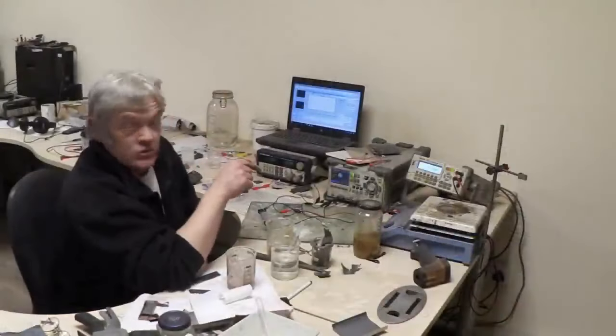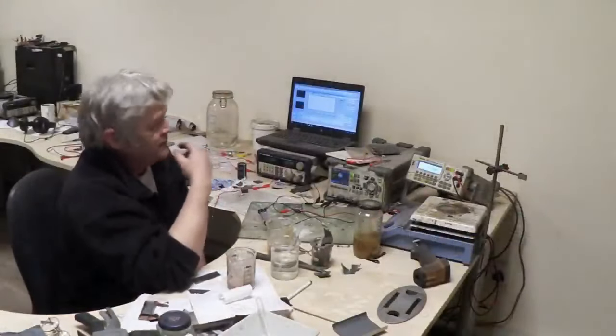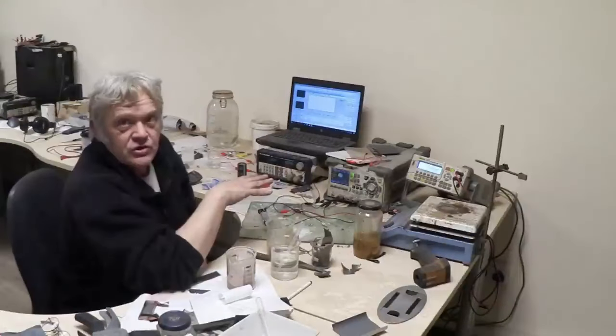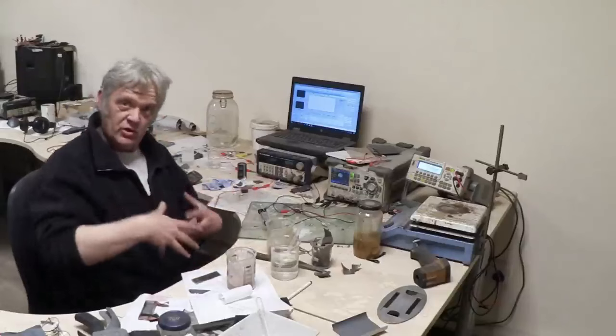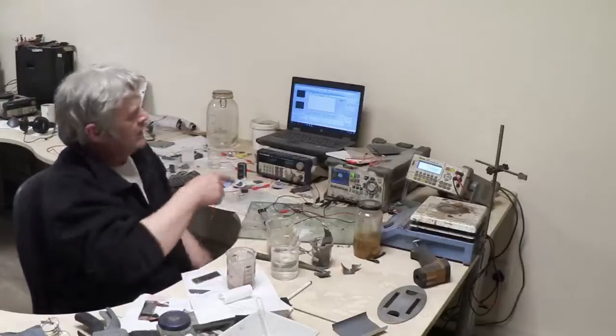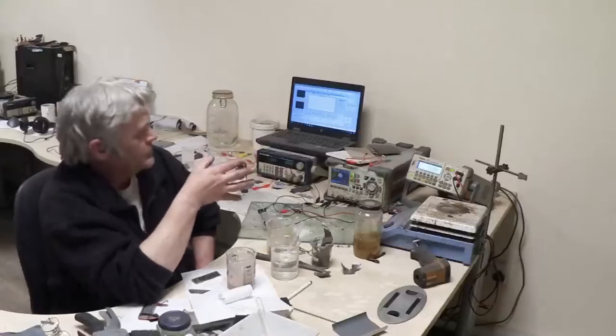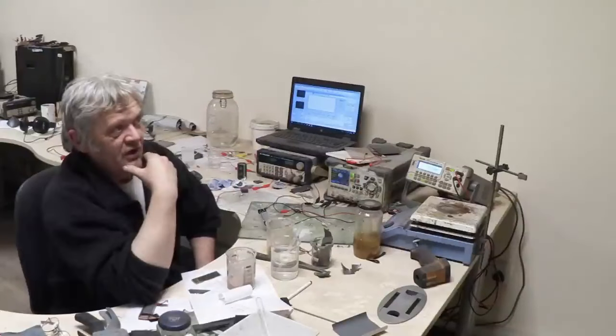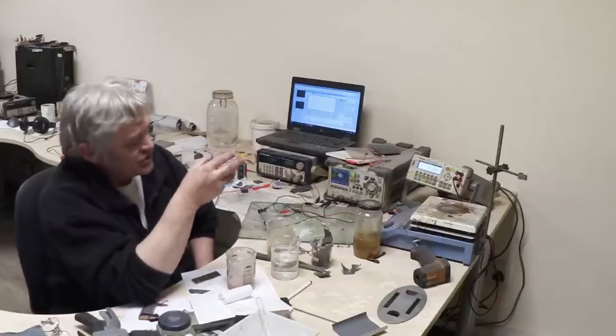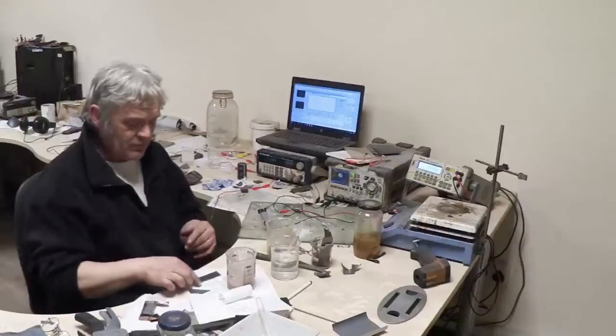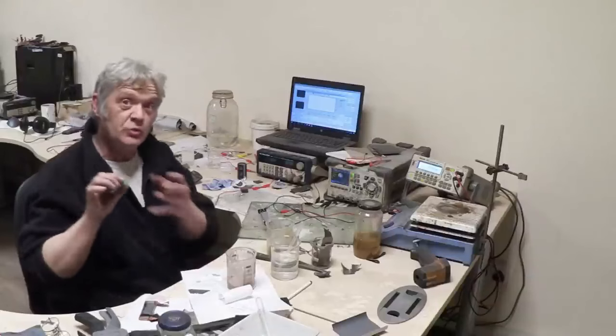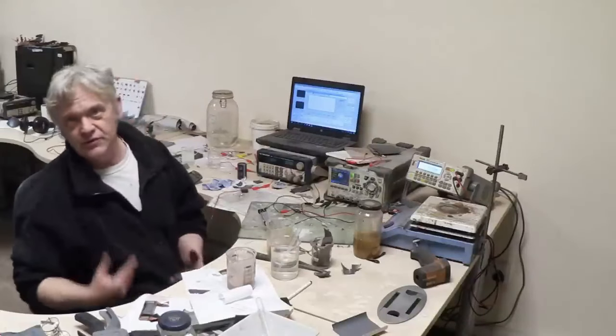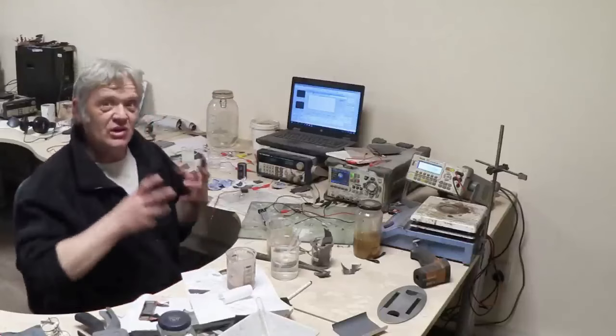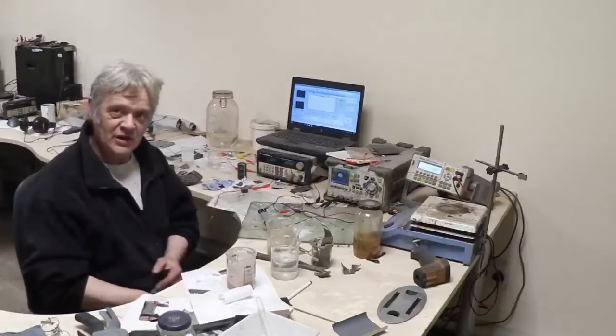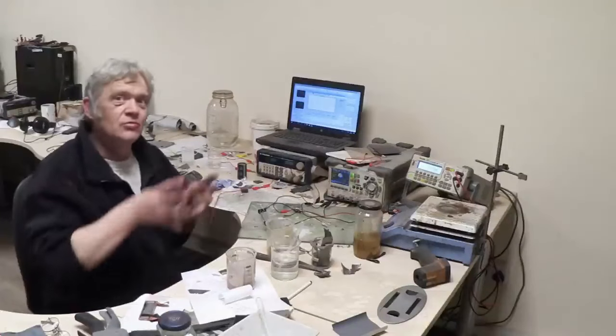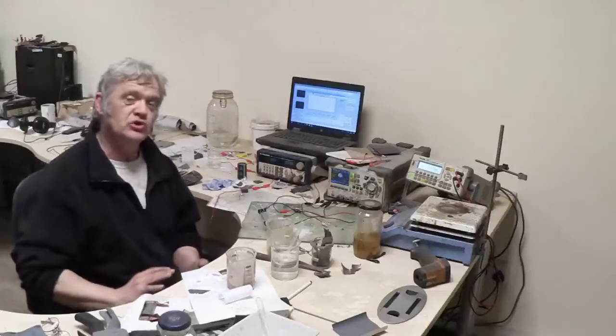Okay, so I've got it on this capacitance meter, which is a Rigol DM3058. It's a pretty decent meter. All I've done is connect a couple of aluminium strips onto it so it can make good contact. And all by itself, without electrolyte, it's around about a nanofarad, 1.078 nanofarads. Now, that doesn't sound like a lot, but when you consider what it is, actually, that's really quite impressive, because something that was physically this size, but two plates of aluminium, will be around about 35 picofarads. So it's a lot more, maybe about 100 times more or something like that. All ballpark figures, but really very much more than it would be just as a plate capacitor.